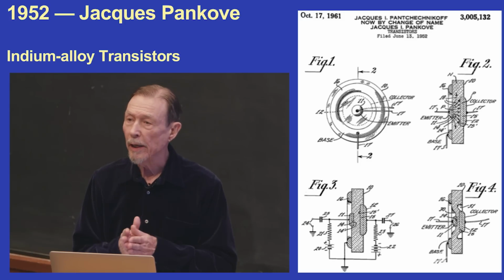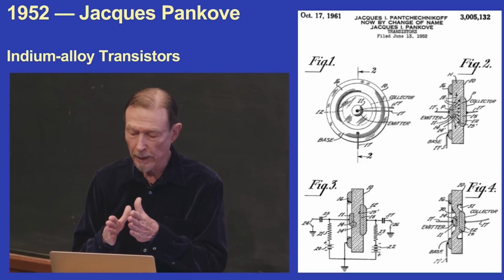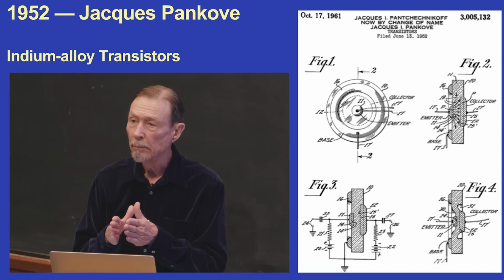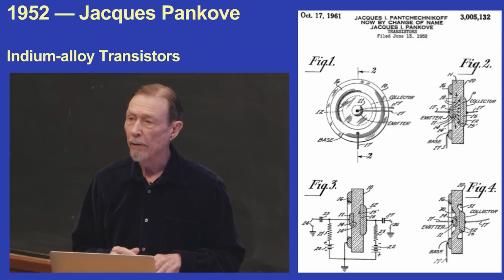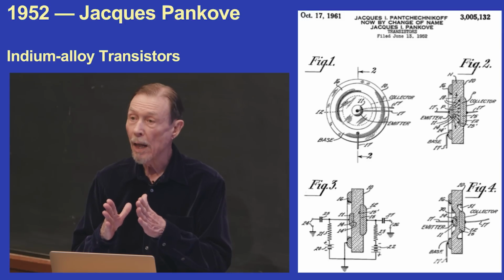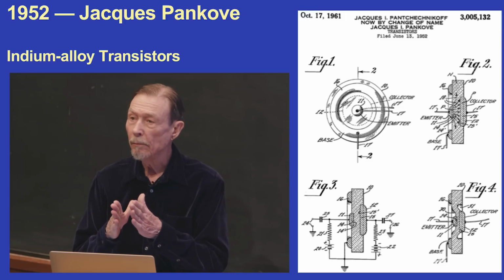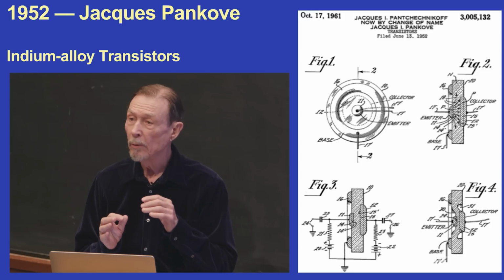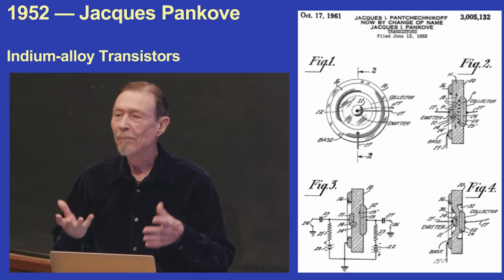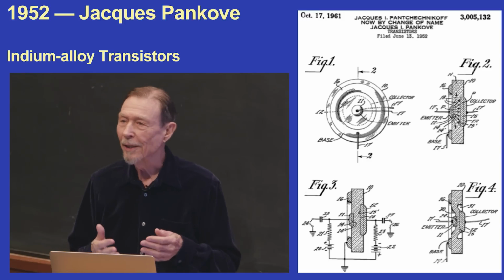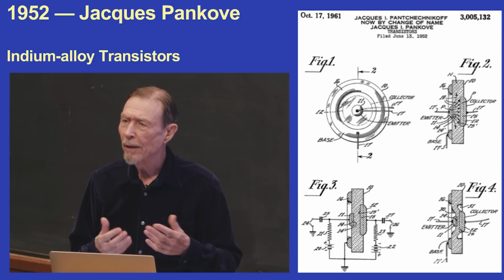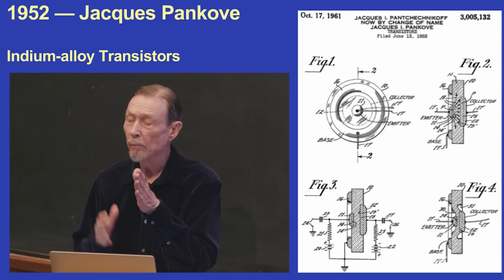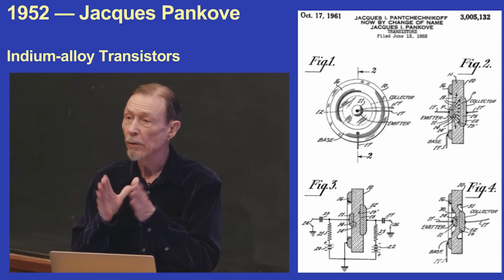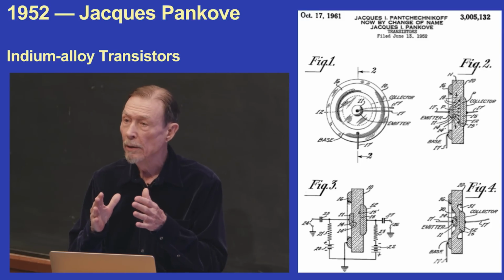You took a piece of germanium and you put a little pellet of indium on both sides, and you put it in an oven until the indium melted. And the indium dissolved a little bit of the germanium. And it was very controllable because the solubility of germanium and indium goes up very slowly with temperature. So you could get a temperature where it went in just a nice controlled amount. And then you cooled it down.